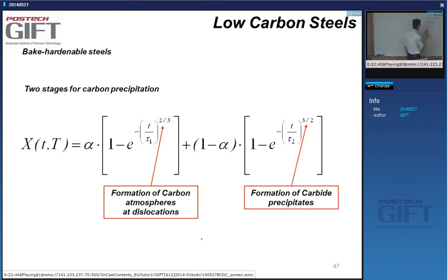Snoek ordering. And what is that? That is the carbon atoms in the immediate vicinity of the dislocations making a few diffusion hops towards the dislocation. That happens very quickly, yes? Because remember, carbon jumps about 1 time per second in the iron BCC lattice. So you introduce dislocations. If the carbon atom is close enough to the dislocation, it will hop to the dislocation and pin it, yes?